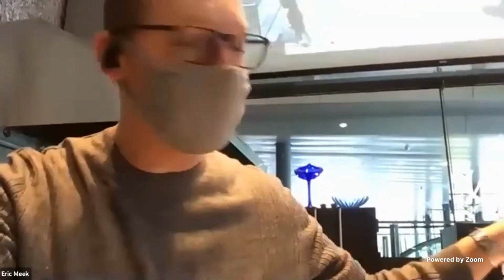And so we definitely are aware of the temperature of the furnace. Now, the reheating furnace, we like that to be hotter than the temperature at which we like to work the glass, because that just gives us a little extra bump of energy. So we're reheating the glass in there. That furnace usually stays around 2300 or 2400 degrees. Now, if I kept a glass in there too long and it got too hot, I simply couldn't control it, and it would drip off the end of the pipe like water. So if we were to get this glass up to 2100, 2200 degrees Fahrenheit, we're talking 1100, 1200 degrees Celsius, it would just become like water and impossible to shape by hand.